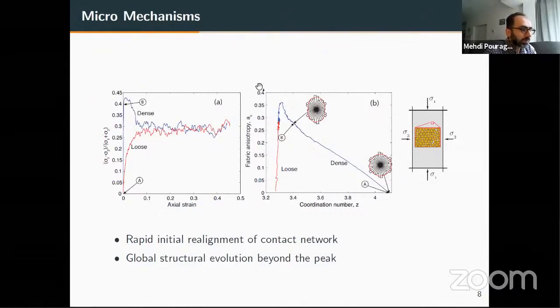Now, when we move to the micromechanical realm, we have a quite different story. Here we are looking at coordination number, the number of contacts, versus fabric anisotropy, which is the anisotropy of the contact network. If you take points A and B for the initially dense sample, in this range not much is happening, and only the deviatoric stress is increasing. But if we look at the contact network, we see that a lot is happening from point A to B.